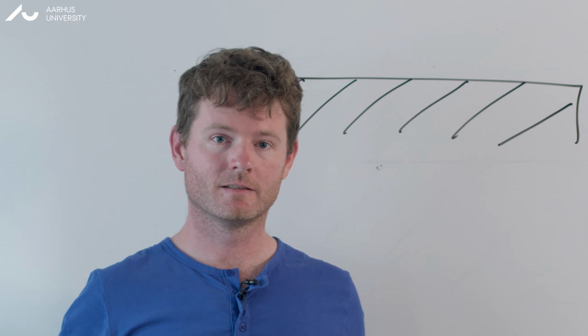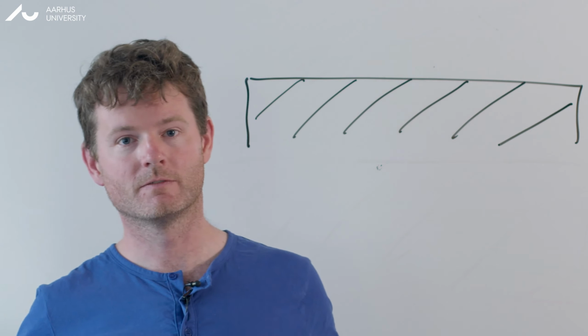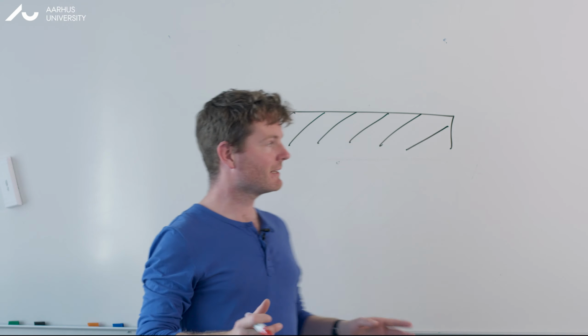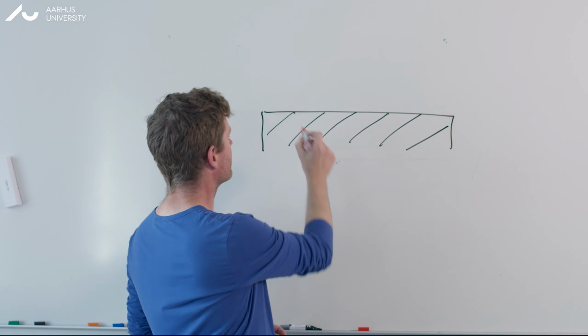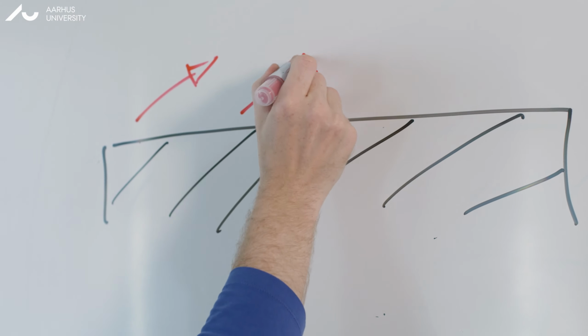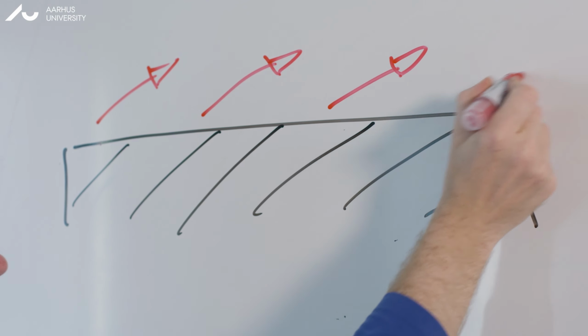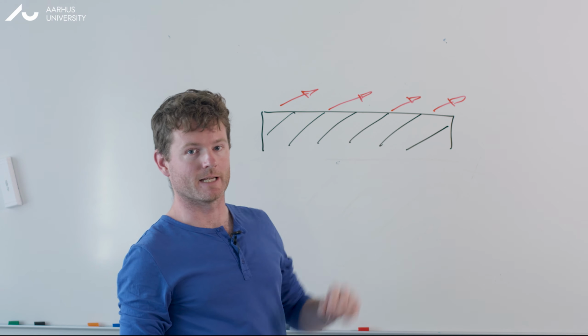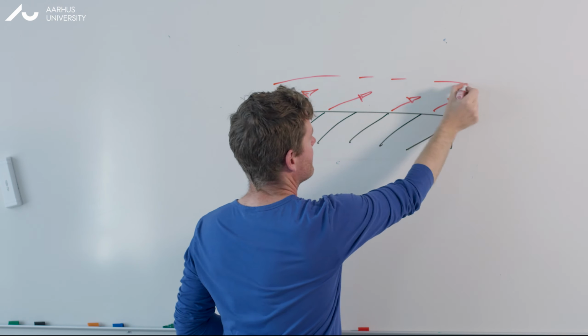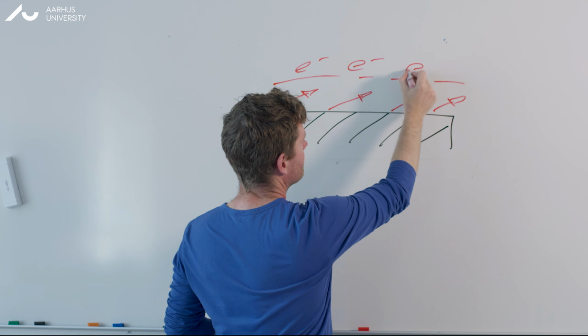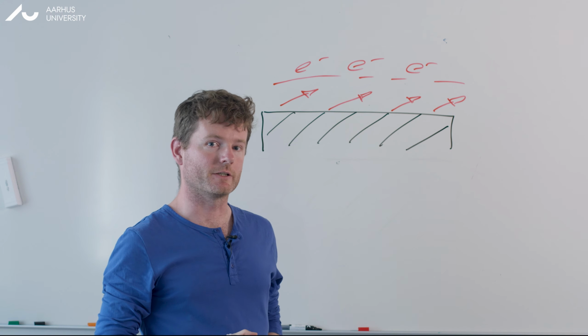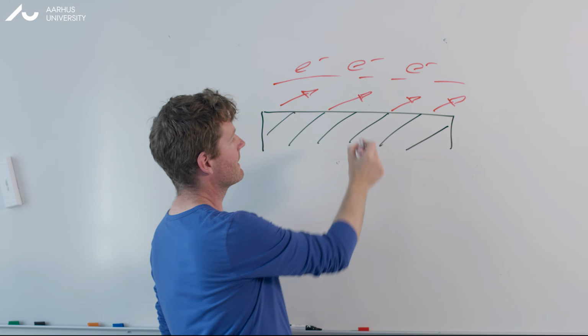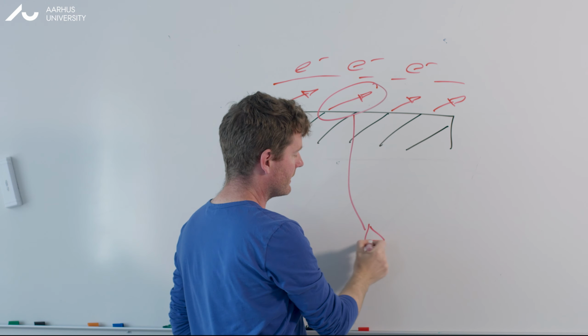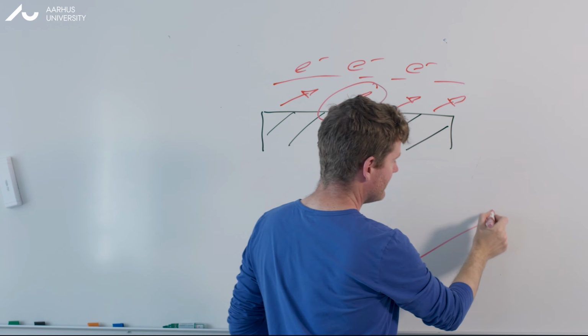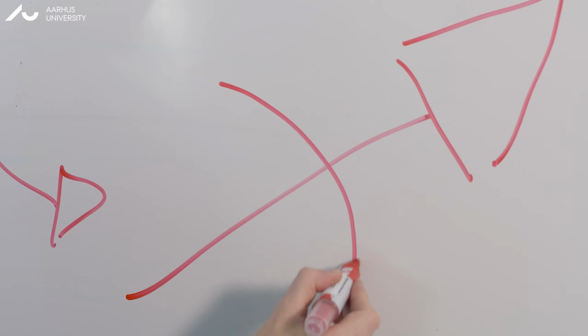The second aspect is the unique handle we get on these materials from the so-called Spontelectric Effect. Methyl formate is an example of a dipolar molecule that, when condensed to form thin films, spontaneously orients so that all of the molecular dipoles, on average, point in the same direction. This results in a polarization charge on the surface of the film, and we can measure the strength of the polarization charge. What we observed was that over time, this polarization charge decreases, which means that the molecules rotate to begin to point in a different direction.